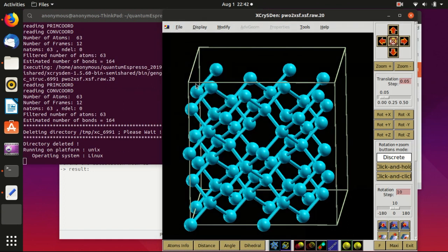I don't know whether we can see or not, but basically the surrounding atoms shrink towards the vacancy a little bit. So we go back to the first image, and then go to the relaxed case, and you see that indeed it goes towards the vacancy a little bit. So this we use as our first image in the energy barrier calculation.